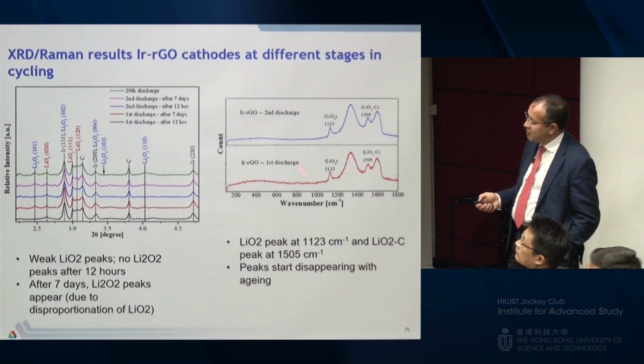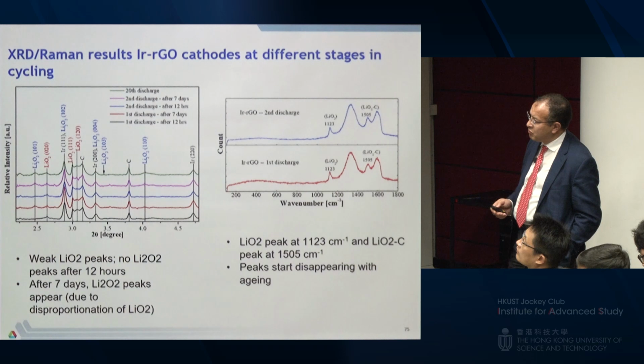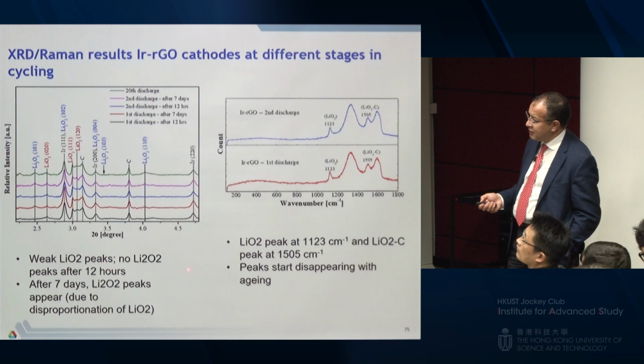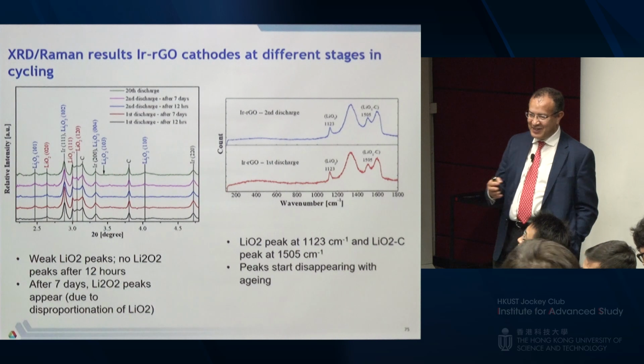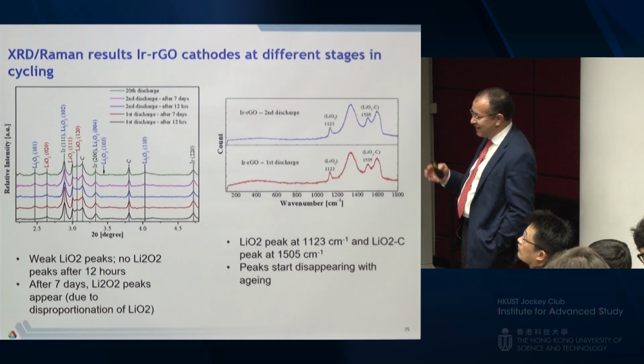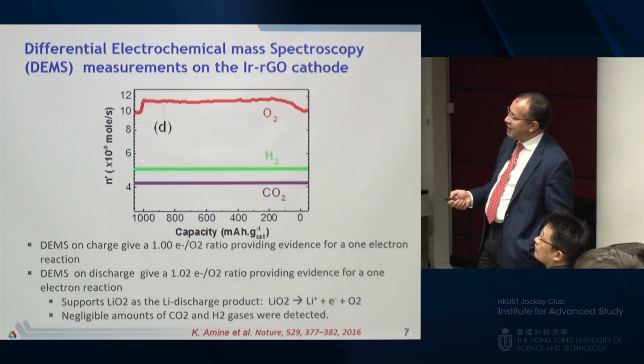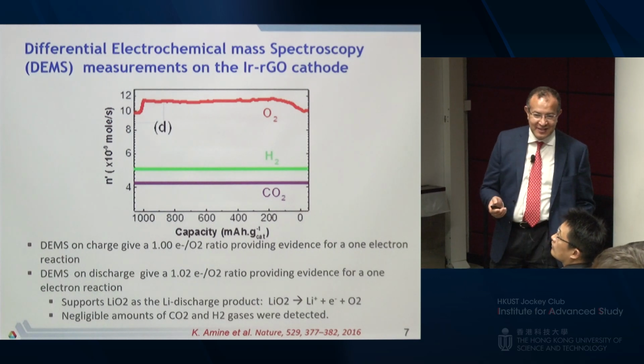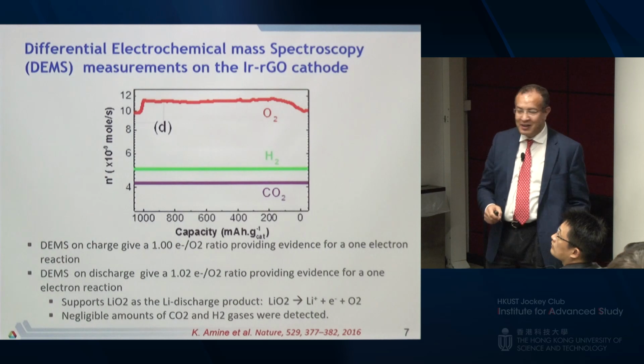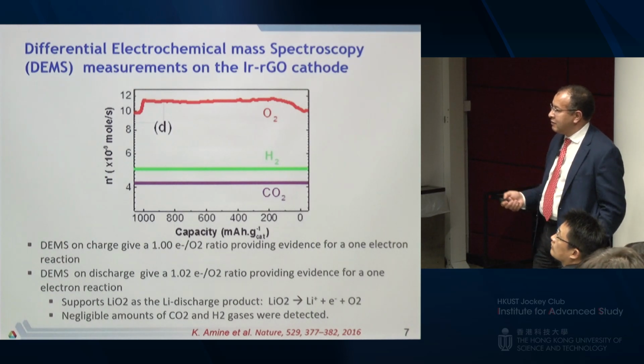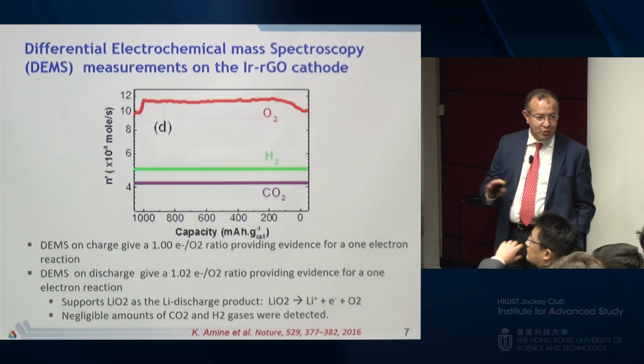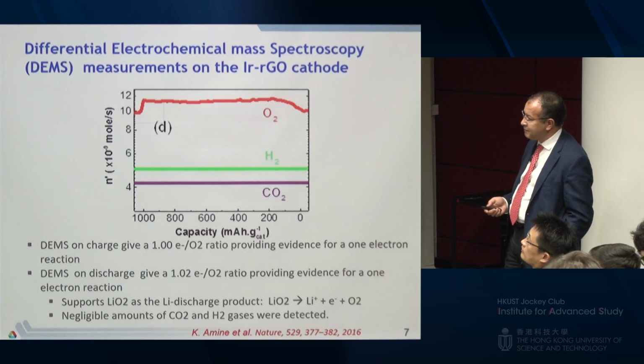And the next step was we ran a Raman, and you can see the signature of lithium superoxide as well in this case. So those are the two proofs, but we have to buy a DEMS because we tried to publish this in Nature, and the reviewer will not accept this result. He wants a DEMS to show that there is one electron transfer. So I spent $200,000 to buy a DEMS, and we did, and we were able to show that it's one electron transfer, which is great. Now we have it. You guys are welcome to use it. It's an institute, and that was a proof that we do have one electron transfer.